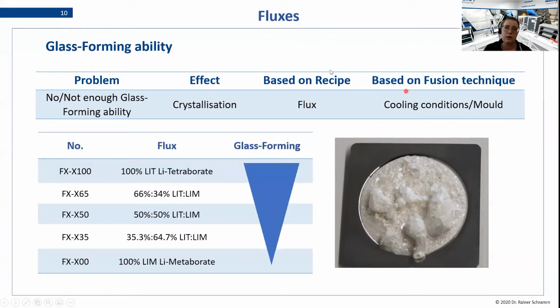But we are talking about flux today. So we are coming back with our very nice table here. And we can see that the glass forming ability of the lithium tetraborate is the highest glass forming ability we are having here. And it decreases the more metaborate is in the flux. So each mixture here that contains more and more metaborate will have less glass forming ability. And that's when something like this happens, this crystallization, when it cannot form a glass anymore, and you will have just some crystal structure here.